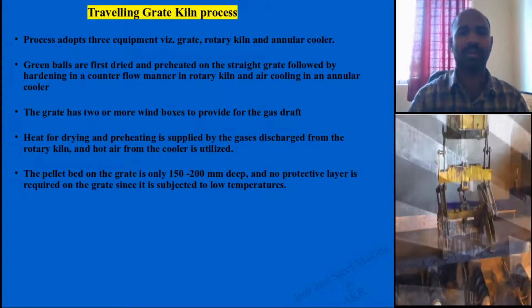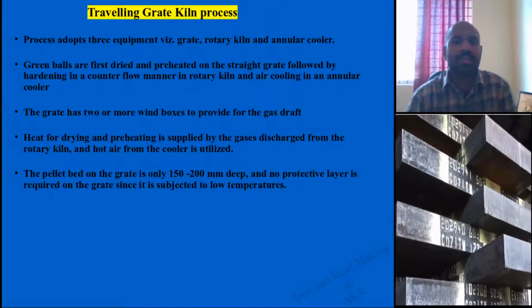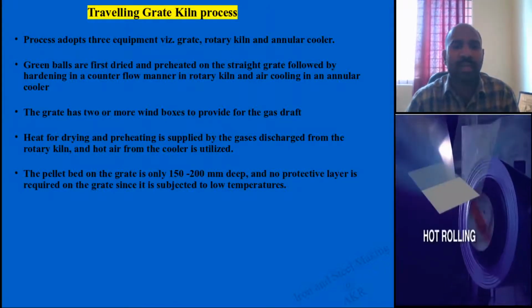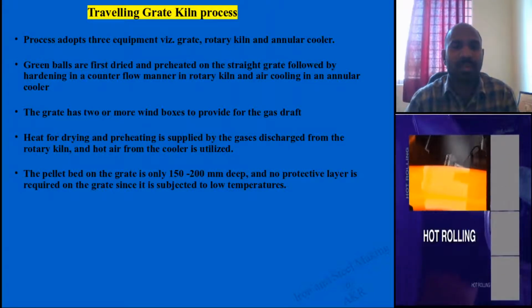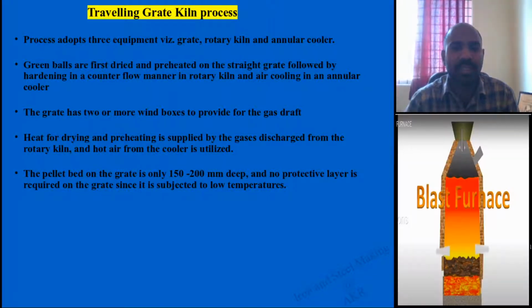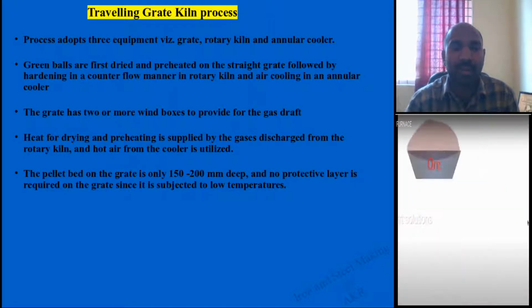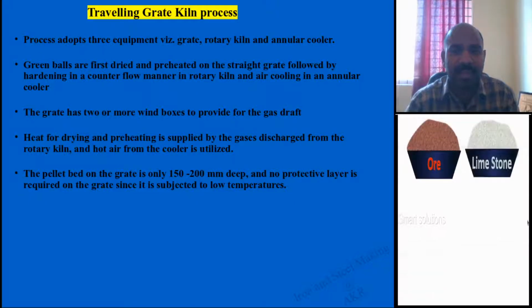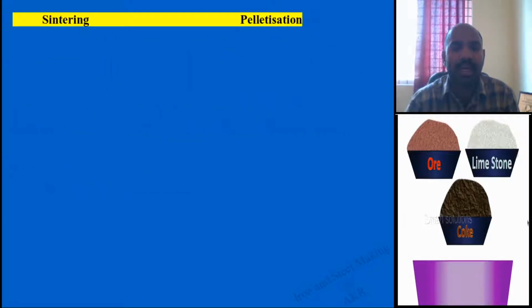The grate depth is maintained at around 150 to 200 mm, and there is no need for any protective layer. It is also a steel grate, and it is moved to the lower temperature section, so that is why there is no need for protection for this traveling grate. You will be getting the hardened pellets.